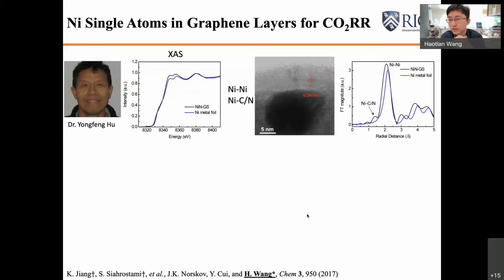But we realized that this powerful technology might not be able to provide us a direct evidence to demonstrate our idea. It is because in this core-shell structure, we have a very difficult time getting rid of these nickel nanoparticles, because our sample will always have these nickel nanoparticles tightly embedded in the carbon matrix. Even if we use very strong acids to try to leach them out, there's no chance to get them out because the graphene is so tightly surrounding them. So as a result, you see that from the XAS, we still get a dominant signal from the nickel-nickel interaction. And compared to the nickel foil, there's only a small shoulder peak. That gives us a sense that there might be a lot of nickel-carbon and nickel-nitrogen bonds, but this is not direct evidence for us to claim this idea.